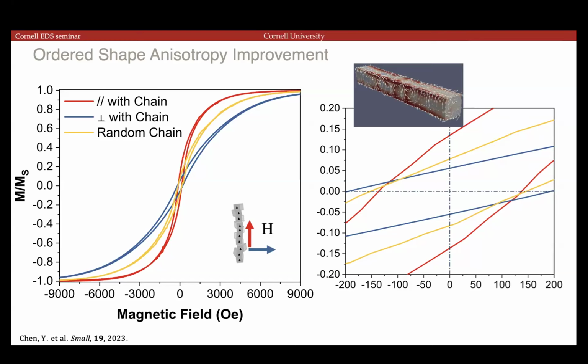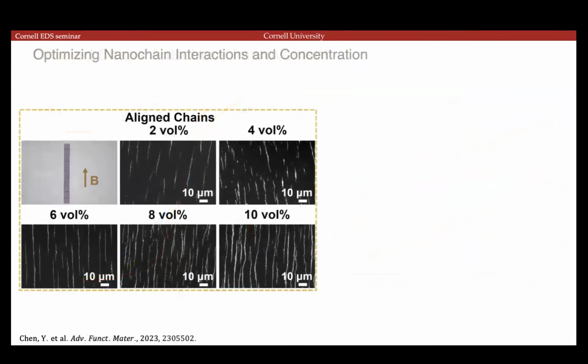The only problem with these particle chains so far is that we're still not getting 100% of the magnetization. That's because when we made the chains, the particles not only grew in length, they grew in width, and they're no longer single domain. If you simulate it, we do have some flux closure inside the nanochain. So the next step is to try to make these not only chains, but also single domain nanochains and hopefully increase that further.